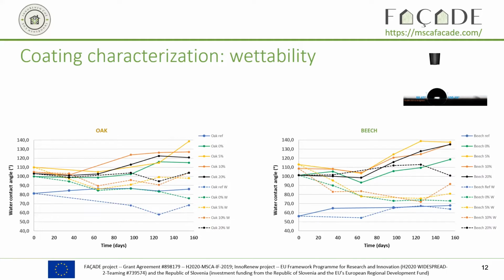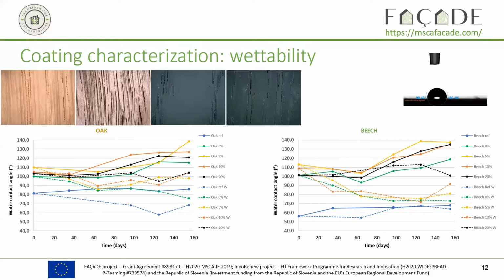Then if we look at the dashed lines now, these are the samples that were exposed outside. You can see that for the reference wood, the water contact angle decreases a lot, even with the coating without biocarbon, this water contact angle decreases. And once we add biocarbon, it is more stable. It decreases, but less. It decreases less, and it decreases the least for the coating with the highest biocarbon content.